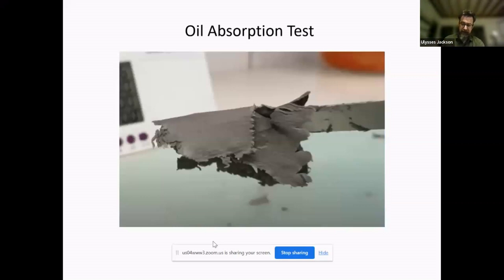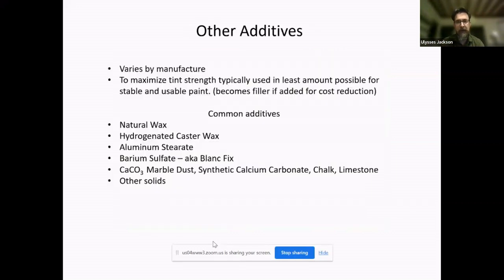Generally a maximally pigmented oil paint will be right at the oil absorption with just enough excess oil to allow it to flow nicely, and then just enough stabilizer to hold that excess oil in place so you don't get separation in the tube. To do that, you use some other additives, and this varies dramatically by manufacturer. For professional artist oils, you're typically trying to maximize your tint strength, right? And to get your tint, you basically need as much pigment as possible, so you're not trying to add anything in excess because it would reduce that tint strength.